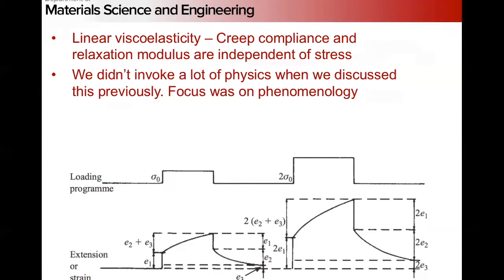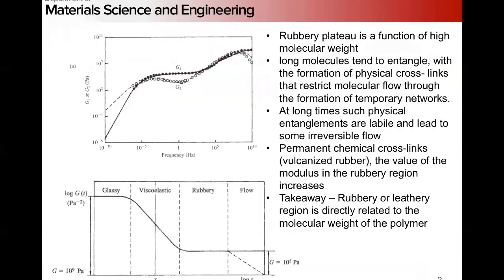So today we're actually going back and looking at some of the actual polymer interactions, right? The chemistry of the polymer chains and the structure of the polymer chains that give rise to this behavior. So if we remember here, if we look at our relaxation modulus, right? Remember at short times we have basically what in the polymer world we call glassy, meaning a Hookean and elastic response. At very long times we have a viscoplastic flow, and in between we have this decreasing region of viscoelasticity, and then for a lot of materials, this rubbery plateau.